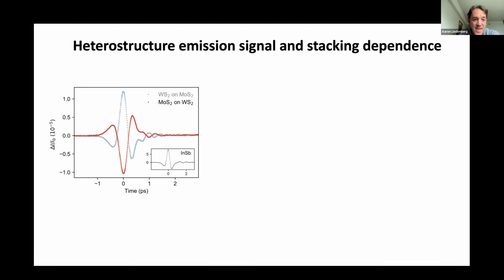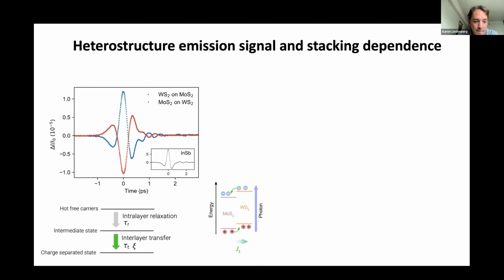Again, the time-dependent electric field that we measure is directly related to the time-dependent current flowing across the material. And then, interestingly enough, if you change the stacking order, so you flip the order in which the heterojunction is deposited, this of course changes the direction of the time-dependent current. This current flips from pointing out of the film to pointing into the film, and this changes the polarity of the emitted terahertz field. So by measuring the polarization state, you can directly extract information not just about the magnitude of the current, but also the direction in which the electrons and the holes are actually flowing.